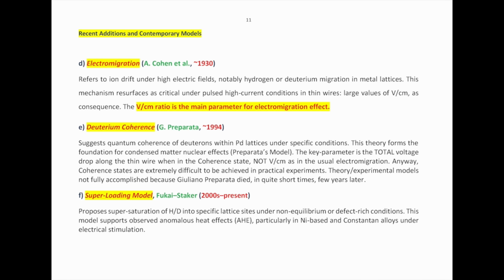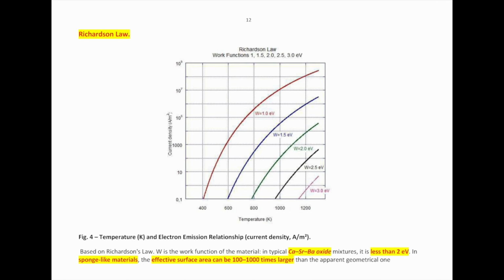The deuterium coherence developed from Preparata is a jump because we consider all the wire where the coherence is made. This is an extremely nice effect, but more difficult to get. So we see it a few times, exciting, but with extremely low reproducibility. And about the place where the reaction happens, we think the superabundant loading model from Fukai can be good.